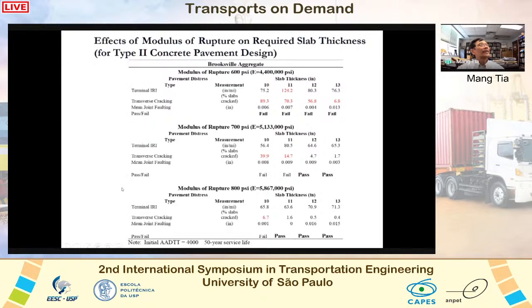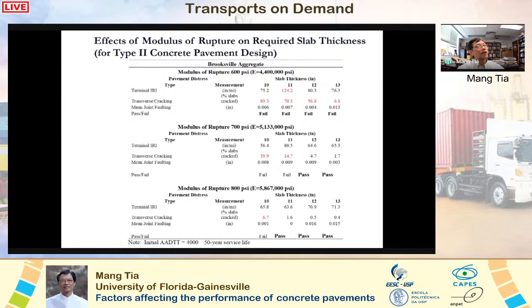Now we look at the effect of flexural strength. We made the analysis with this concrete using the good aggregate, and we vary the modulus of rupture from 600 psi to 700 psi to 800 psi, and we want to see if increasing the modulus of rupture, which is the flexural strength, makes a difference. And the answer is yes. When you increase the flexural strength, as you can see here.